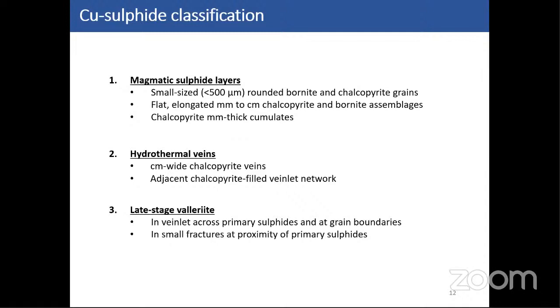So the sulfides here are considered to be magmatic because they are trapped in the host rock. And they show the three textures I mentioned before. So the small bornite and chalcopyrite grains, with some complex grains with both bornite and chalcopyrite, some flat elongated assemblages, which can reach a length of about 1 centimeter. And the last type is chalcopyrite and millimetric thick cumulates. The second main category consists of hydrothermal veins, which can be more than 1 centimeter wide, with adjacent sulfide networks within the surrounding gangue.